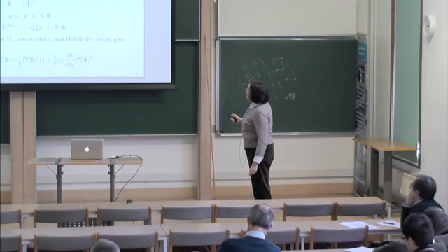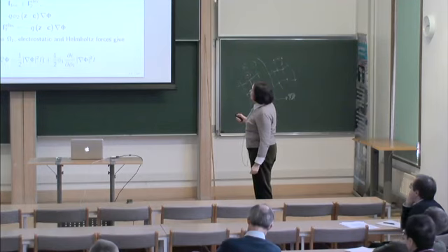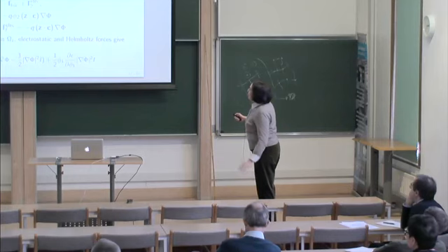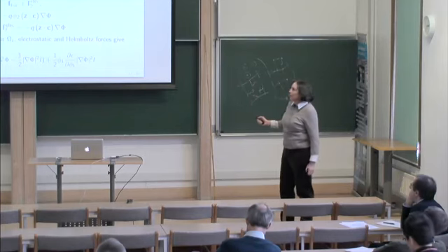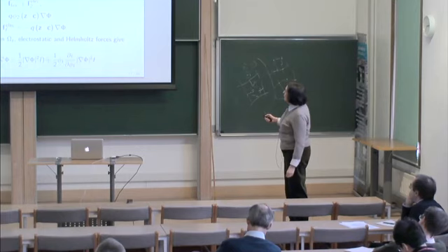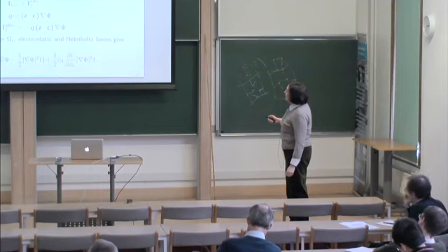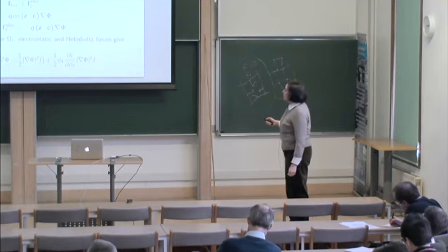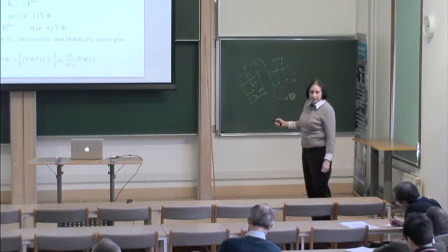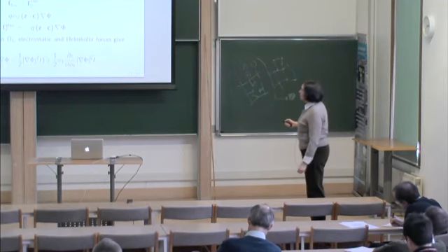And then here there are a couple more forces. First of all, this would be what we would call the Lorentz force, right? And then there is another force called the Helmholtz force that is not there if the dielectric coefficient is constant. So if the dielectric coefficient depends on the volume fraction, we get the Helmholtz force.